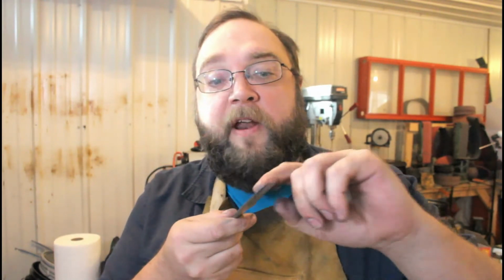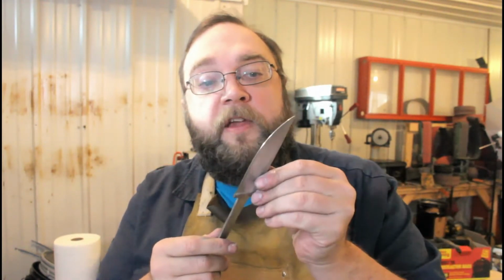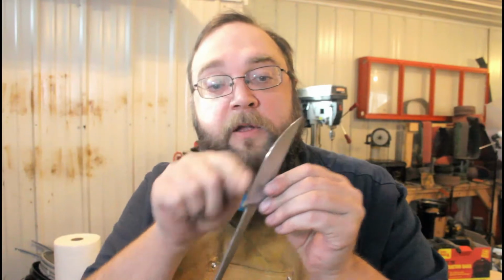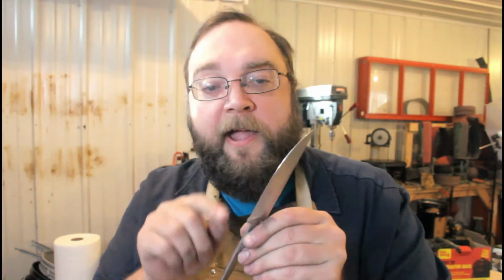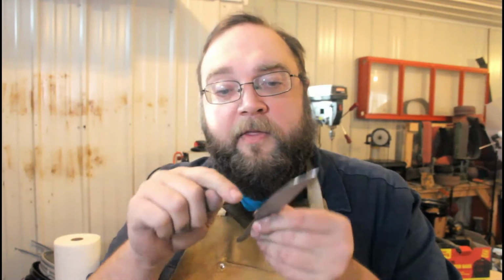The next thing to do is put a little ferric chloride on here and see how we did with our 52-100 high carbon edge. Now that does matter. That needs to be fairly even so that when we go to heat treat this, hopefully it doesn't warp or crack or do anything crazy.